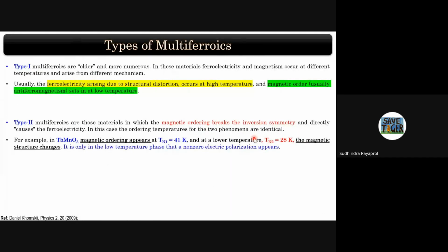So this is what makes the multiferroics very interesting to us. Now, if you go deeper into this, there are two types of multiferroics. You have type 1 multiferroics, which are older, which were originally observed, where the ferroelectricity arises due to structural distortion, which occurs at high temperature, and the magnetic order, usually antiferromagnet, sets in at low temperature. In this type of multiferroics, you have both the ferroelectric and magnetic orders present, but they are independent of each other.